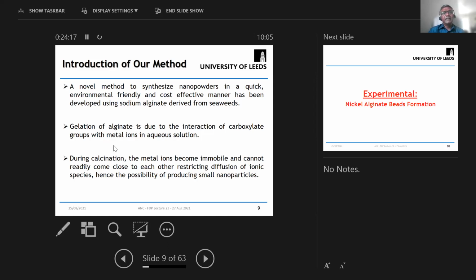During calcination, the metal ions become immobile and cannot readily... So this is a very important step. If this was not present, then it won't yield nanopowders. But incidentally, during the calcination, the metal ions become immobile and cannot readily come close to each other in the open structure of the alginate ion exchanged beads itself, thereby restricting diffusion of ionic species and hence the possibility of producing smaller nanoparticles instead of coarser particles due to sintering at nanoscale.